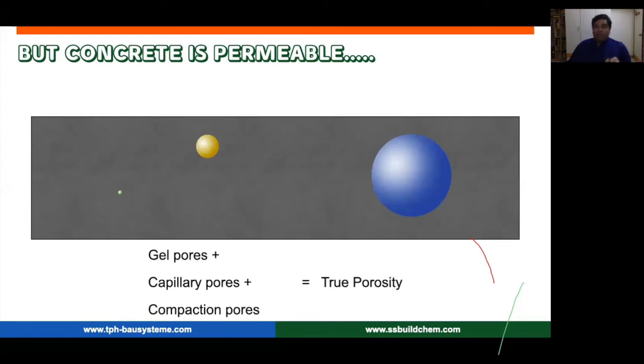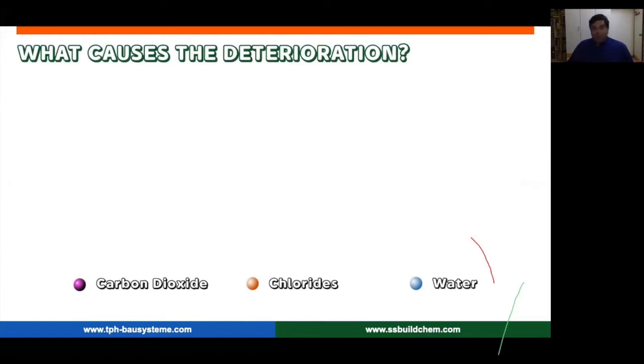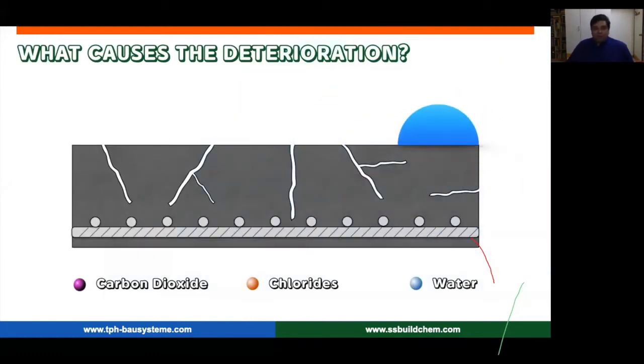And last is your compaction pores. This comes because of air entrainment into your mix, or because it's not compacted properly. And these voids are pretty large. Going from your gel pore to your compaction pores, it's almost about 500 to 1,000 times the size of this tiny pore out here. And these two, basically your capillary pores and your compaction pores, are what we are here to treat by using integral waterproofing systems.